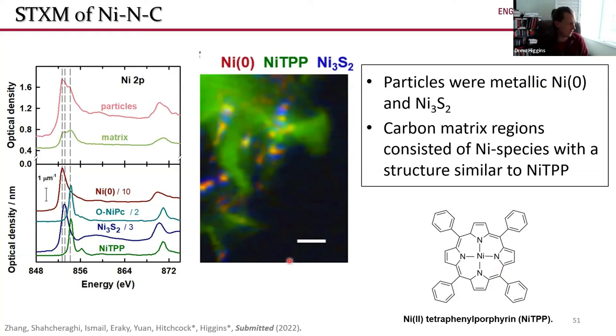The other thing that we notice is that when you look at these reference compounds, the nickel TPP peak is actually quite narrow because obviously it's structurally homogeneous. But in terms of the active site structures or these coordinated nickel structures we saw in our carbonaceous materials, that peak was quite broad, which tells us that we have some distribution in the exact identity and structure of the active site materials present in these catalysts.